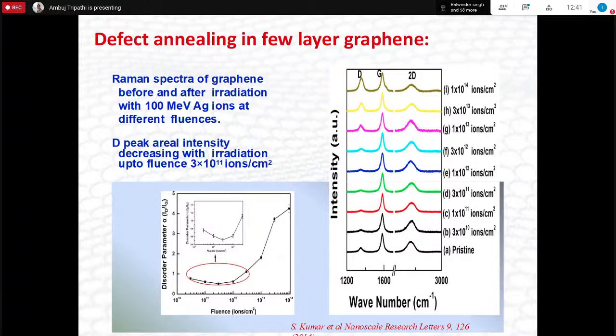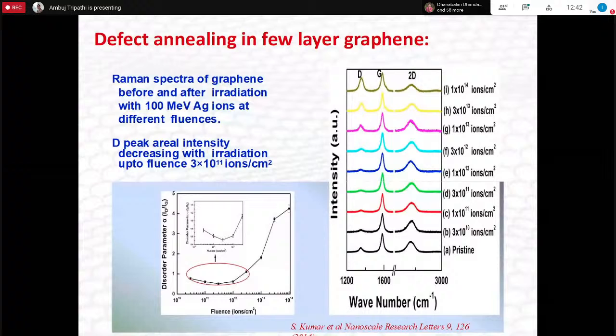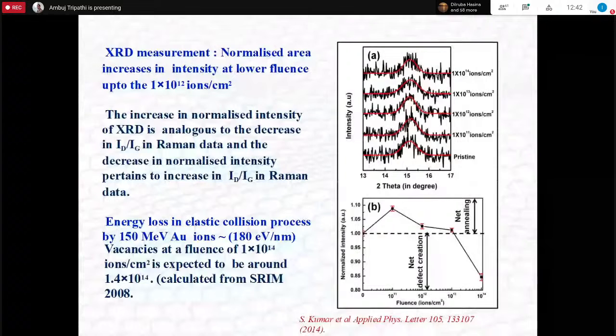So as the D peak changes, that is what is plotted in the left side curve, and you can see that initially annealing happens. So the damage disorder goes down and then it starts increasing. Our explanation was that initially the halos overlap, so annealing happens, and then gradually the cores start overlapping and the damage happens. So this is how it was done. There are 3 papers on these results. One is in Nanoscale Research Letters. Then it was further extended, and this was in Applied Physics Letters. This is all part of Sunil's thesis work.